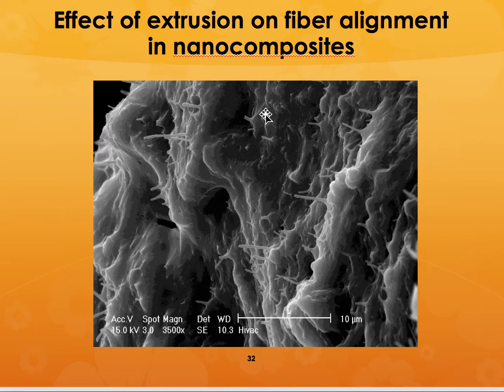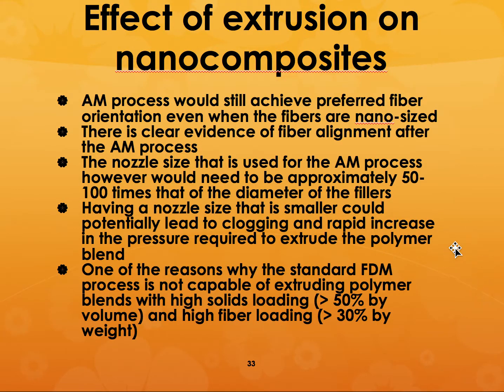Now, you can also see on the fracture surface itself, these small fibers sticking out in these nanocomposites. I believe this is vapor grown carbon fibers because this doesn't look like the nanotubes themselves. But you can see the alignment in the direction of the extrusion. So, what did we find? We found that additive manufacturing process can still achieve preferred fiber orientation even when the fibers are pretty nano-sized. And there is clear evidence of fiber alignment after the additive manufacturing, but the nozzle size has to be pretty large. It has to be at least 50 to 100 times that of the diameter of the fillers.